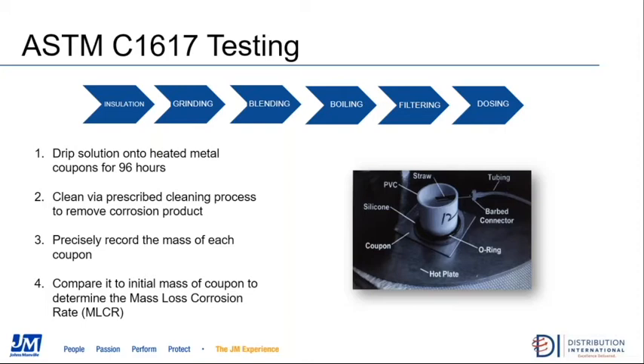The sample preparation process includes weighing that metal coupon before you start the testing and preparing the solution that will be used to evaluate the impact of the insulation material on the corrosion rate. The insulation material is baked initially to drive off any residual moisture that might be in it. It's ground into a powder and then mixed with DI water, allowed to sit to give any contaminants within the insulation material an opportunity to leach into the solution.